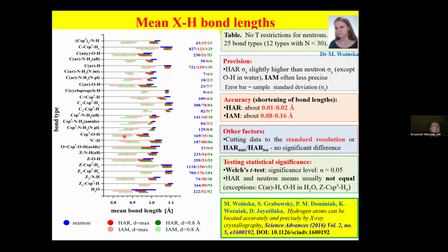We compared our results with neutron data. So there are only like 4,500 neutron structures, and when you focus your attention on the very best quality single crystal, troubleless structures, you can get different types of bonding to hydrogen atoms, as enumerated here. So these are different classes of bonding to hydrogen atoms. And this blue color is showing the distribution of neutron values. This deep red is showing results of